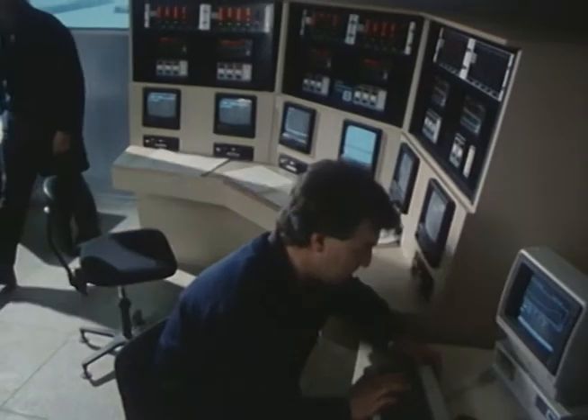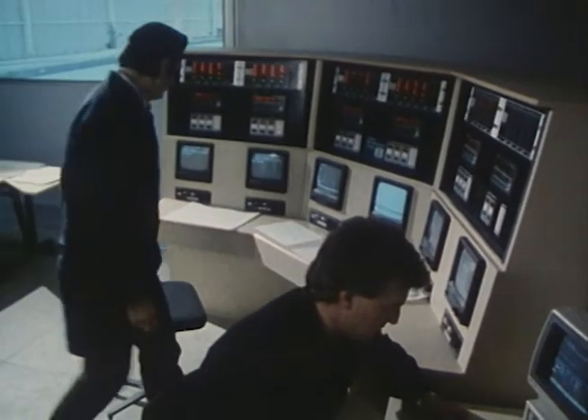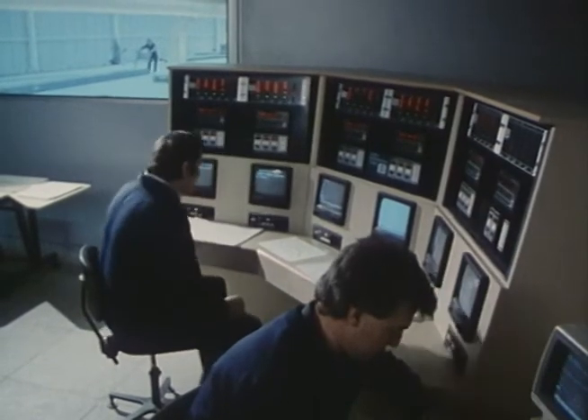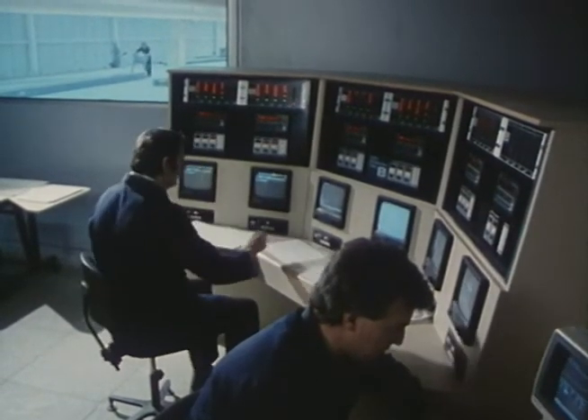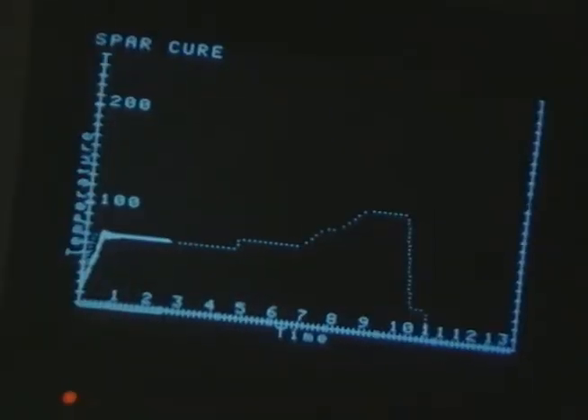The press control room starts and monitors the computer-controlled cure cycles in the presses. Heated press platens take the tool and composite to 75 degrees C. At this temperature, the resin system reaches minimum viscosity and the mandrel bag is slowly inflated to 200 psi, forcing the composite into the female spar mold profile. Then the press is taken to 125 degrees C for a curing dwell of 80 minutes.